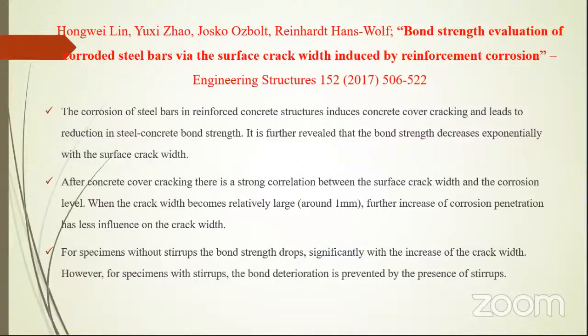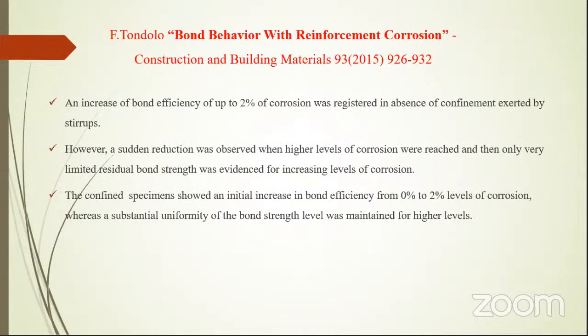When the crack width becomes relatively large, further increase of corrosion penetration has less influence on crack width. For specimens without stirrups, the bond strength drops significantly with the increase of crack width. However, for specimens with stirrups, the bond deterioration is prevented by the presence of stirrups.